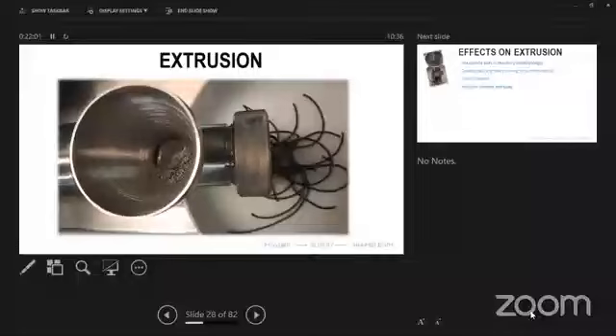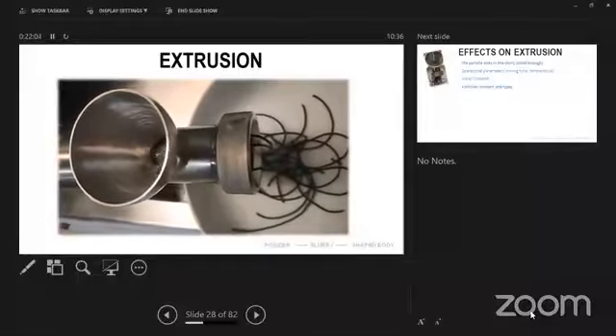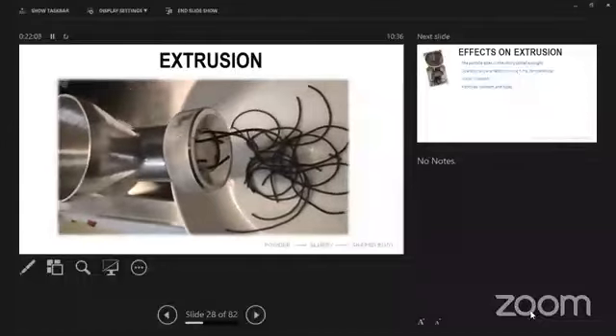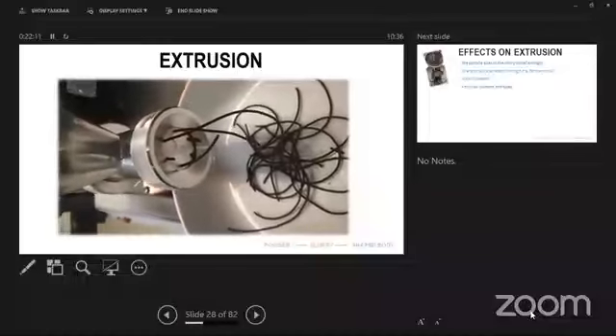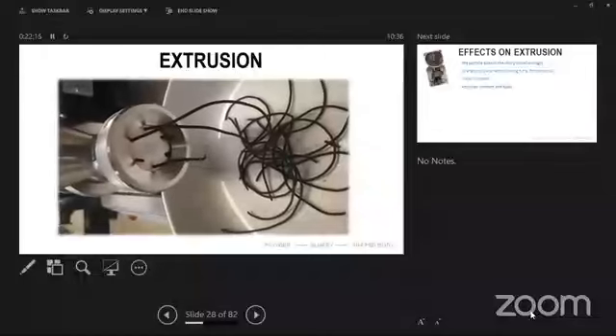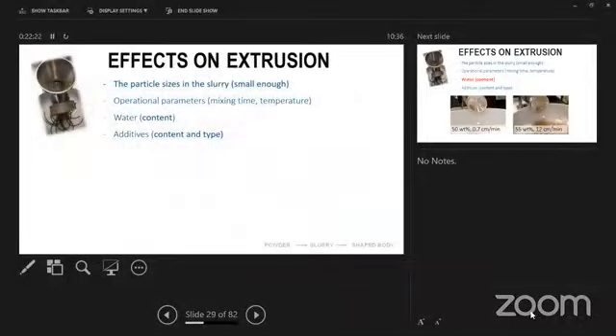So this is an example of extrusion. You see, we put the paste in and then we have some extrudates coming out. Once again, we don't have the cutting device, so we cut all that manually. So what are the parameters affecting extrusion? The particle size in the slurry should be small enough. Then operational parameters, mixing time. Temperature typically is not really a parameter. Everything is done at room temperature. When you do extrusion of plastics, it's done in the molten phase, so then you really need to melt the polymer. Here it's just room temperature. Water content, this is extremely important. I will show a few examples. Additives, the content and type.